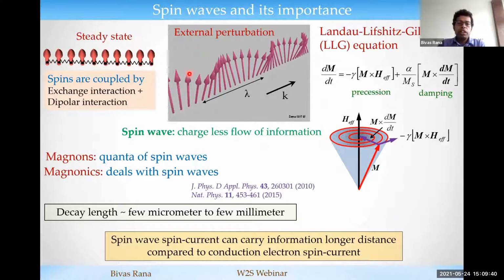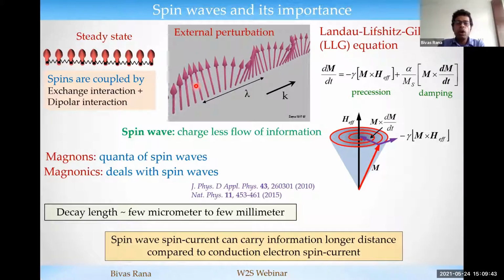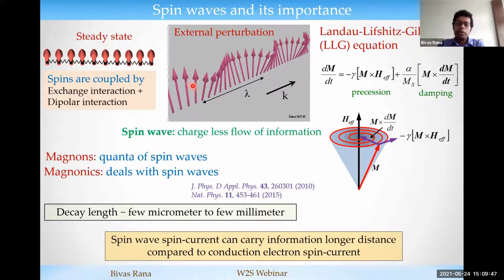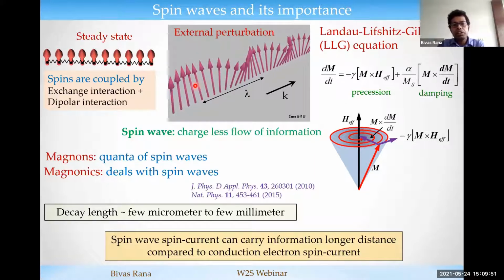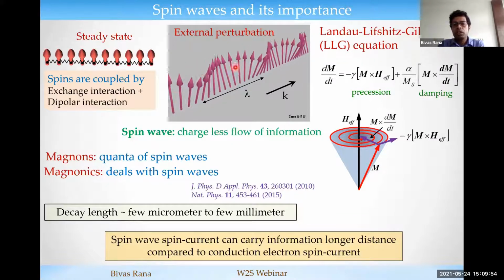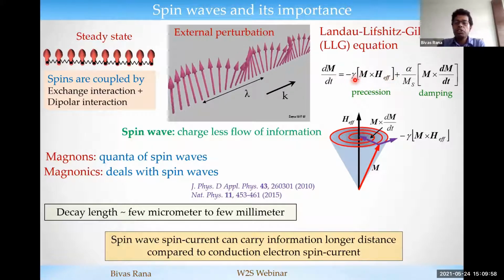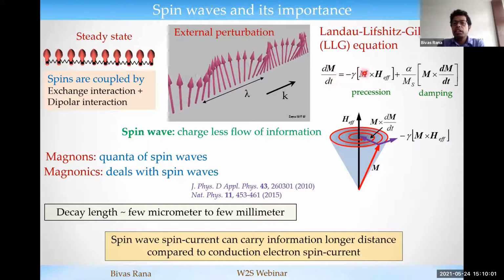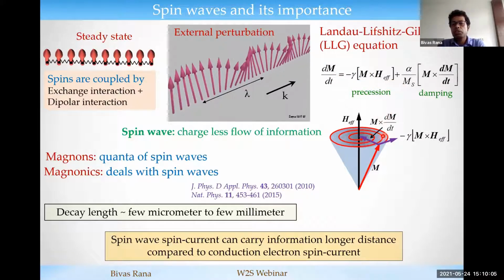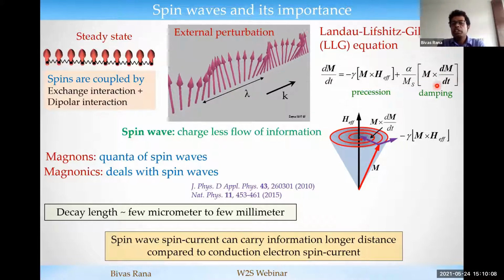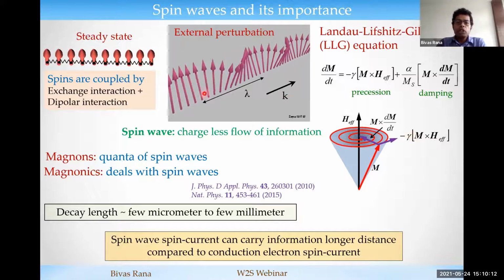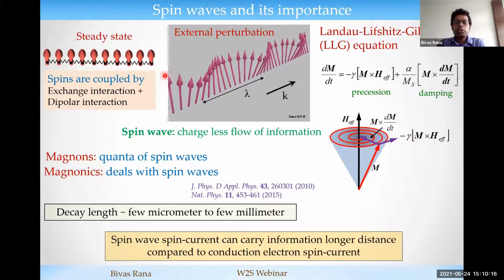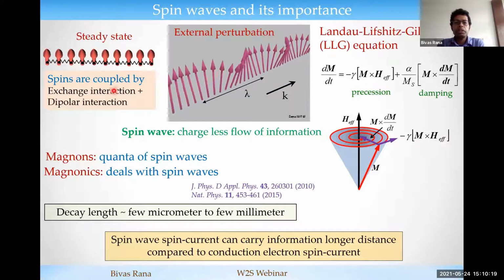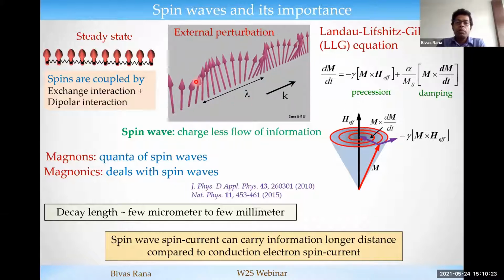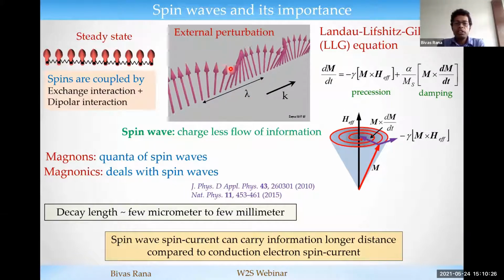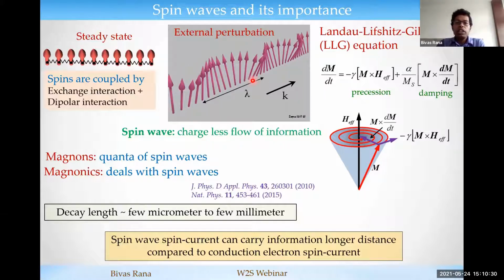Now, if we perturb some of the spins very locally, by using, let's say, temperature or an electric or magnetic field, then the spins start to precess around the equilibrium position. That is governed by the Landau-Lifshitz-Gilbert equation, which shows that the time rate of change of magnetization is composed of two terms. One is a precessional term that is responsible for the precession of magnetization, and another is a phenomenological damping term. When this group of spins starts to precess, other spins coupled with these spins by exchange and dipolar interaction also start to precess. But there is a phase lag, of course, and the phase of this oscillation moves along the wave path. So this is called the spin wave.